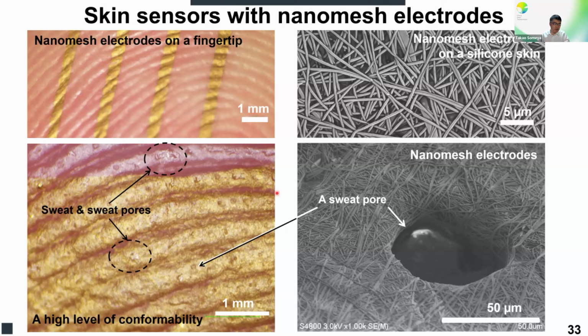And also this is a magnified photograph, and again the shining part is nanomesh, and the non-shining part is bare skin, and the dark spots are sweat pores. And if you look at the sweat pore region, both on the gold region and also the non-covered region carefully, we observe the same amount of sweat penetrating from the sweat pores. So this means that the natural penetration of sweat and the natural vaporization of sweat are not prevented because of the breathability.